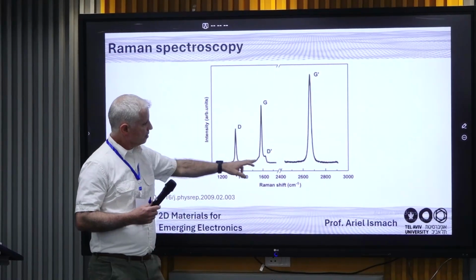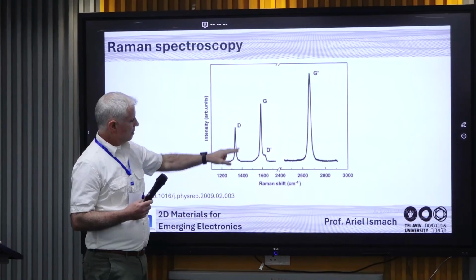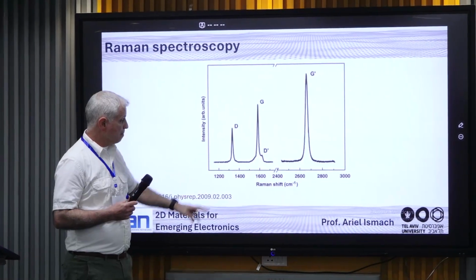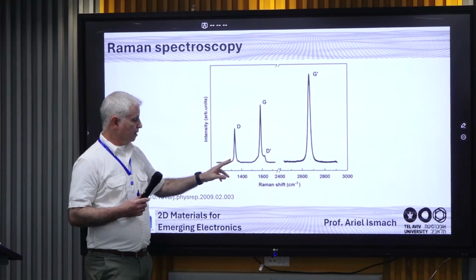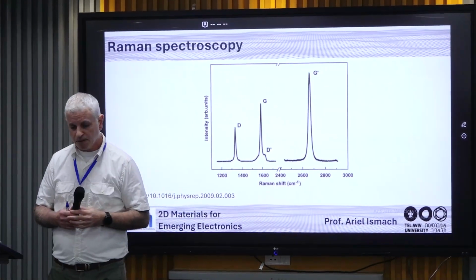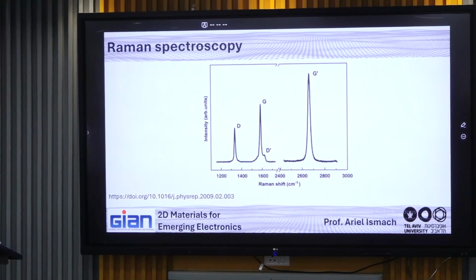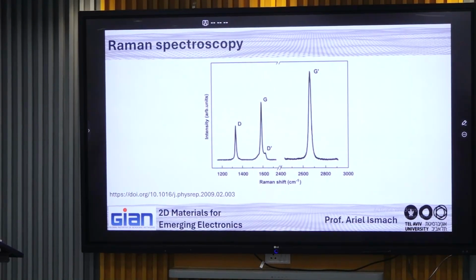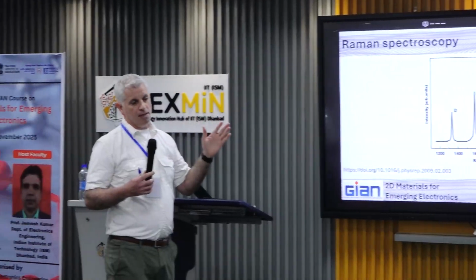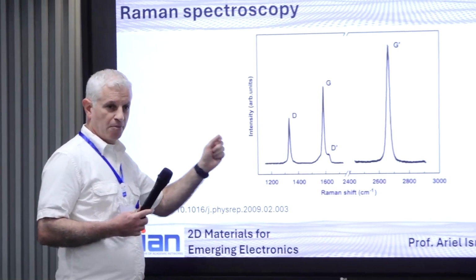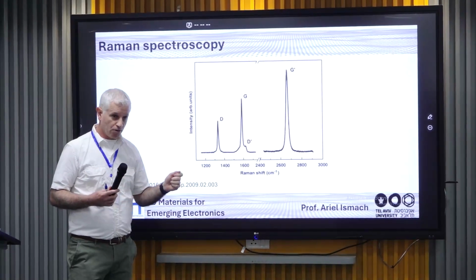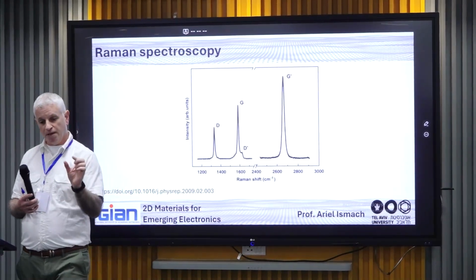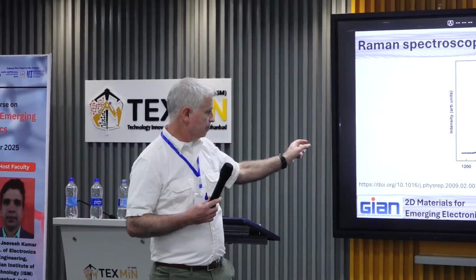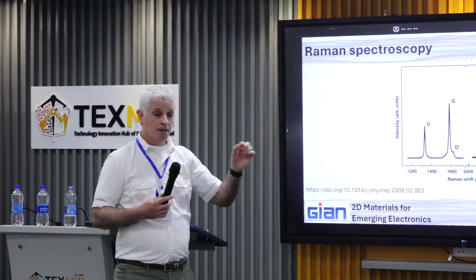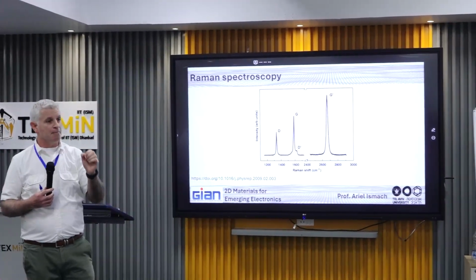Now, maybe because of the D peak here, this ratio is a bit different. The D peak here shows you that you have a lot of defects, but that the sample is very crystalline, because otherwise you would get a broader peak. And the thing about spectroscopies in general, any spectroscopy, the sharper the peak, it means that the material is of higher quality. Why is that? Because the signal that you're measuring, it doesn't matter if it's a Raman signal from a specific mode or another spectroscopy, if it comes with a very narrow distribution, that means that they are all coming from the same type of events.